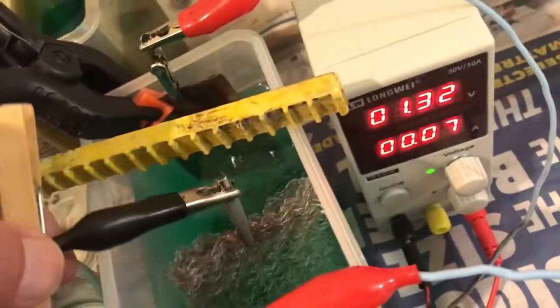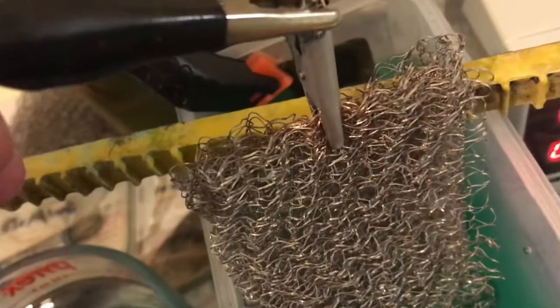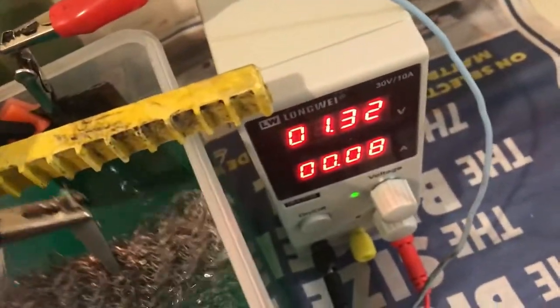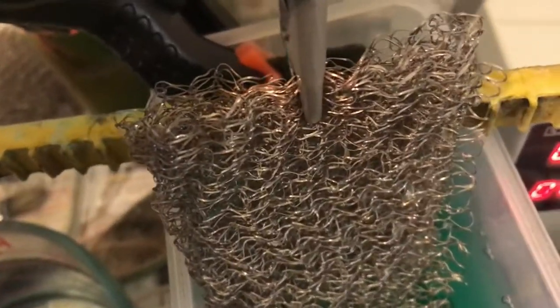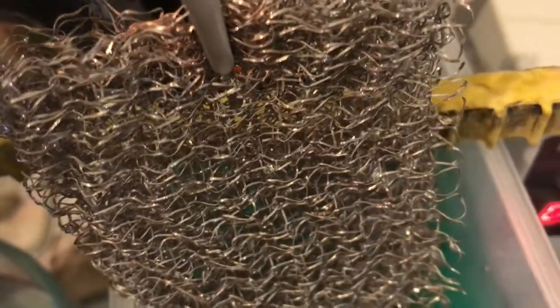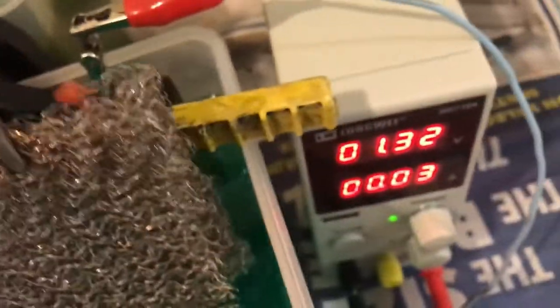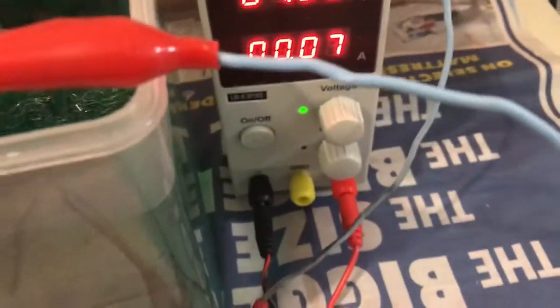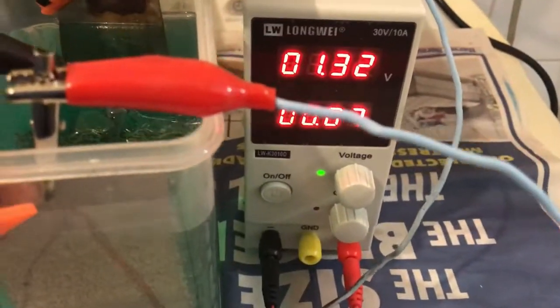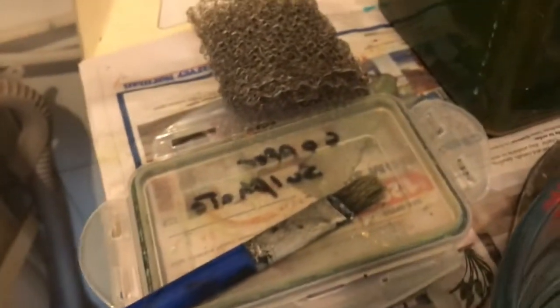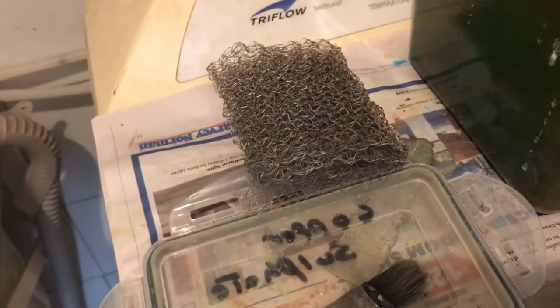I think this one's been in here for about 9 hours or more, and it's almost completed. See those bubbles? When you have a higher amperage, it covers it in bubbles and it doesn't plate. So this is much better at 70 milliamps for that type of mesh. I've folded it over 4 times, so it's completely coated in nickel. That may increase the surface area of the batteries.